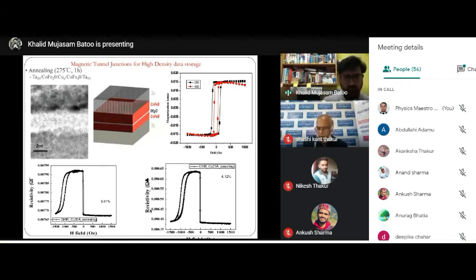However, when doping with copper, we saw that the percentage of TMR, that's the magnetoresistance, is changing from 3.31 to 4.52%.